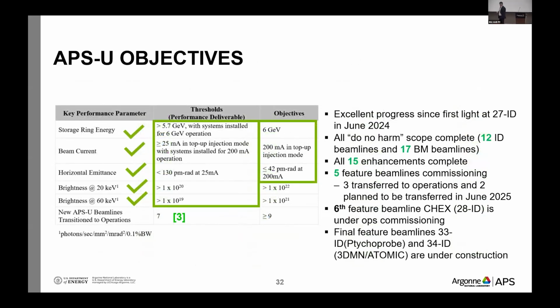So all of the machine parameters have been demonstrated, 200 milliamps of current. The threshold parameters don't mean a lot, to be honest. But the objective ones, they mean project success, but I don't think they would be acceptable as a cutting-edge facility by themselves. We want to be on this side of the graph. So 6 GeV, 200 milliamps, we demonstrated better than 42 picometers. We think that when all the gaps of the undulators are closed, we will be close to 20 picometers in both planes. That's something that we will measure as we restart.